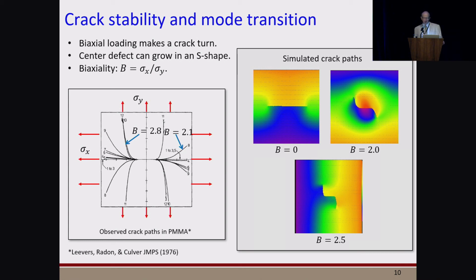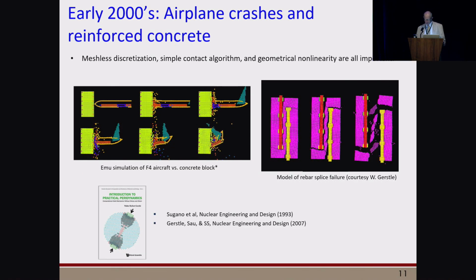is sufficient, it becomes energetically favorable for the crack to turn. And this is a form of crack instability because it can grow either one direction or the other, resulting in these S-shaped looking crack trajectories that are reflected in the simulation.